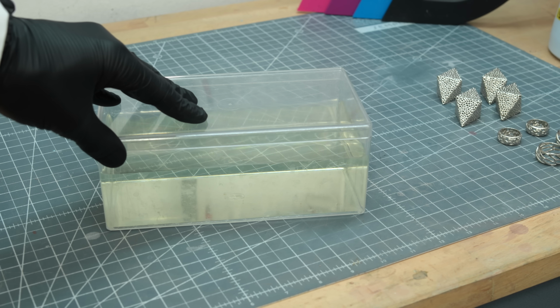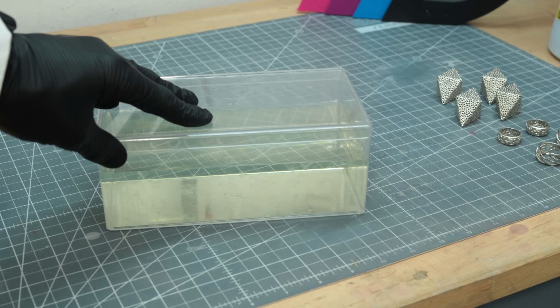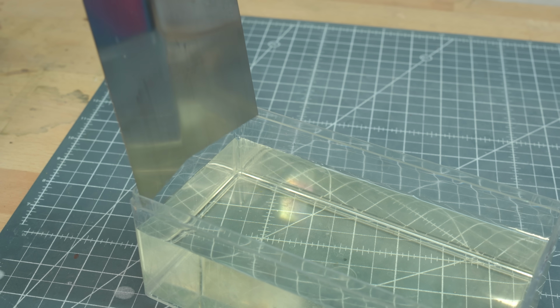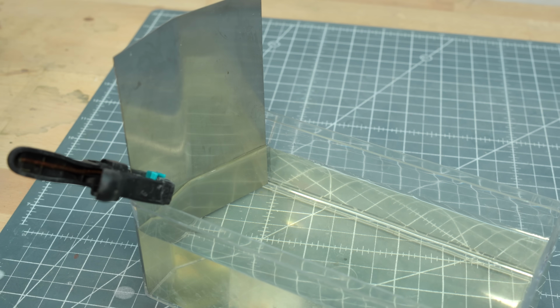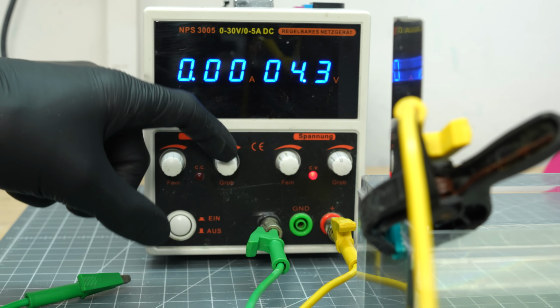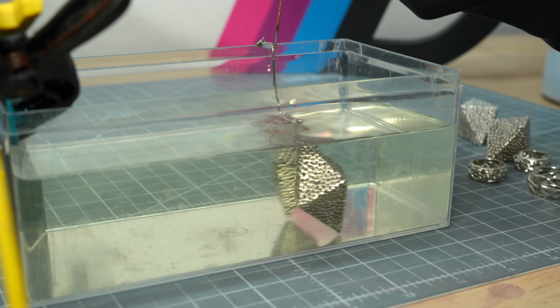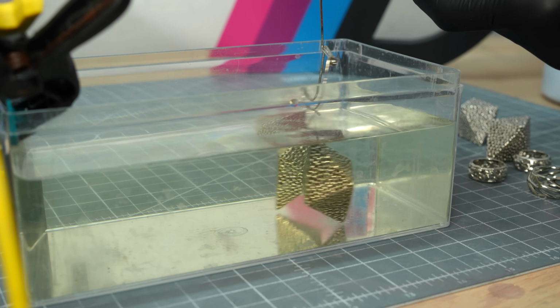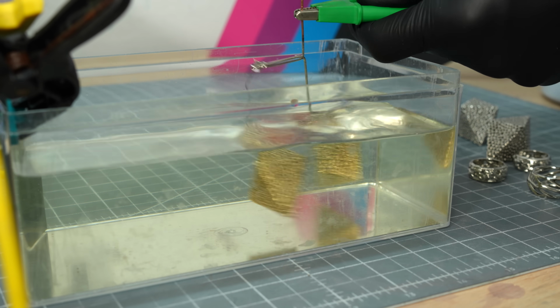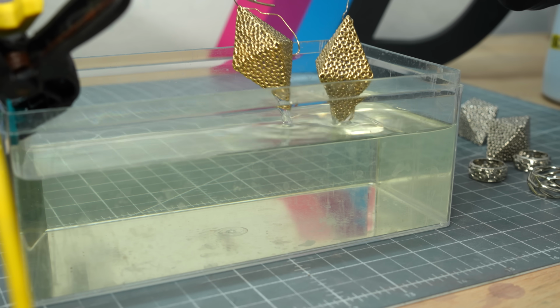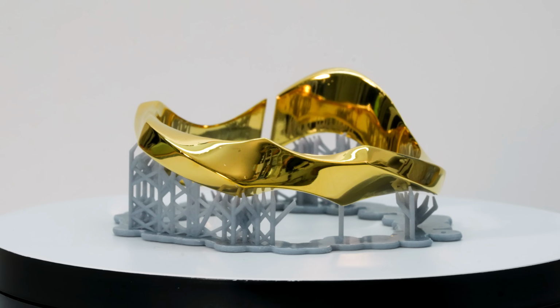And that's what I show you now. This is a gold electrolyte bath. It works just like the other baths using a suitable anode. Here stainless steel, but graphite also works. And the appropriate current. I'm using constant voltage here and doing it by feel. The gold deposits quickly, and the longer the object stays in the bath, the thicker the layer becomes. Never let the electrolyte come in contact with any acid. Here are a few examples.